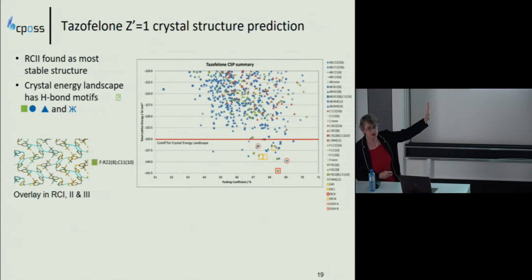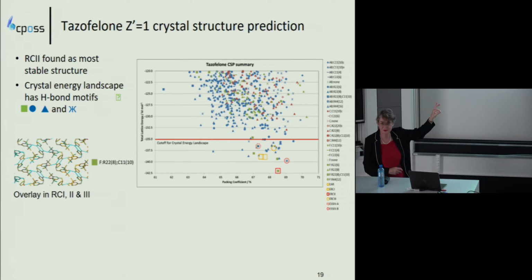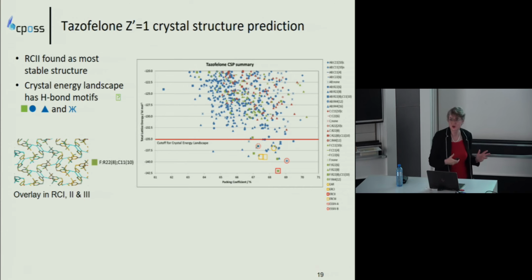So generated all these crystal structures, which Louise lovingly classified by type of conformation in colour and type of hydrogen bonding motif. And of those that were generated, only a few need to be worried about. One of them, the green squares, are that hydrogen bonded layer in the observed racemic forms, and yippee, the most stable Z prime equal 1 structure has been found. The other two are low in energy, but because they're Z prime equal 2, two different molecules, you wouldn't expect to find them. But we've got a few more, one's hiding there, green squares there.